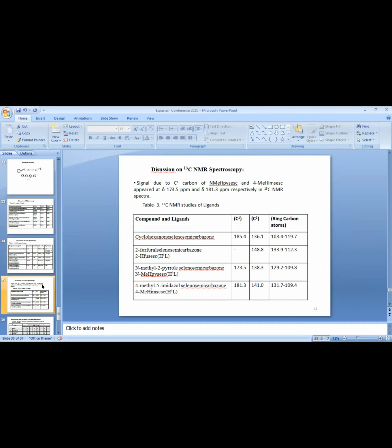Now, discussion on carbon-13 NMR spectroscopy. Signals due to the C1 carbon of, for example, N-methyl 2-pyrrole selenosemicarbazone and 4-methyl 5-imidazole selenosemicarbazone appeared at 173 parts per million and 181.3. They indicate that the compound as well as the related ligands have been prepared.